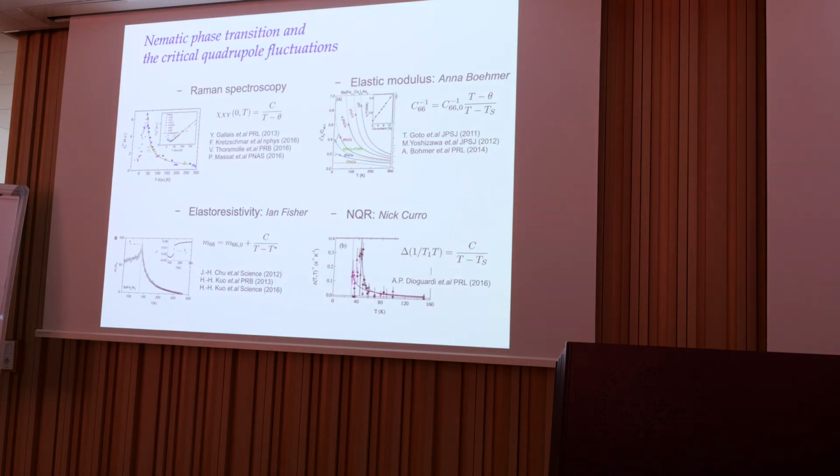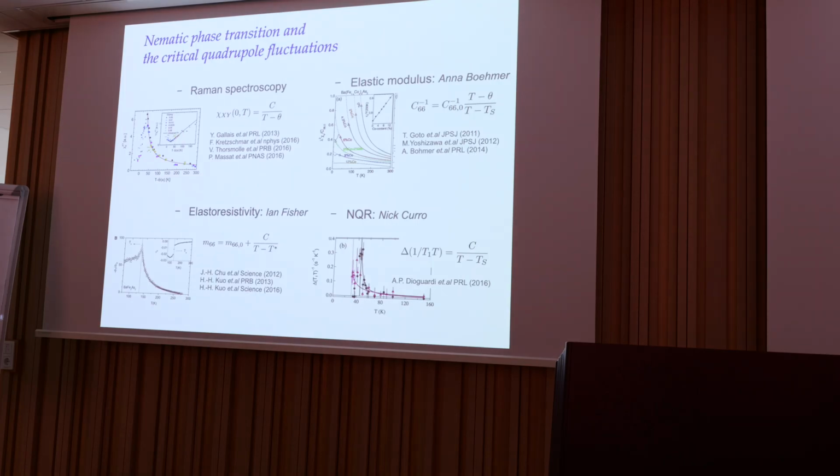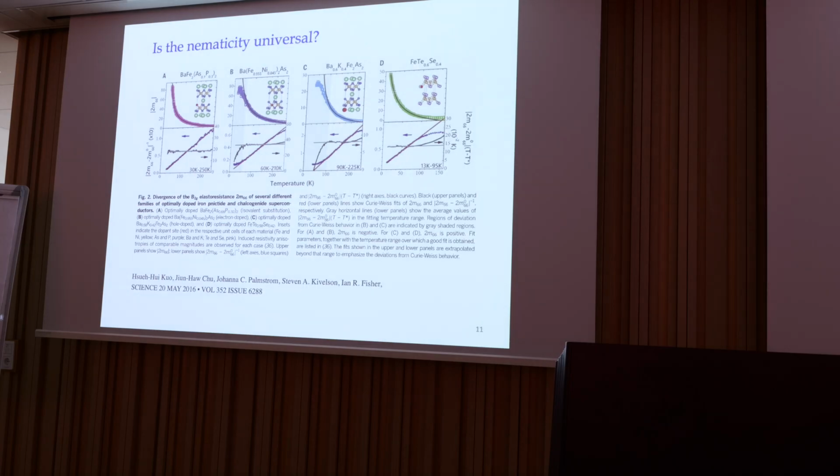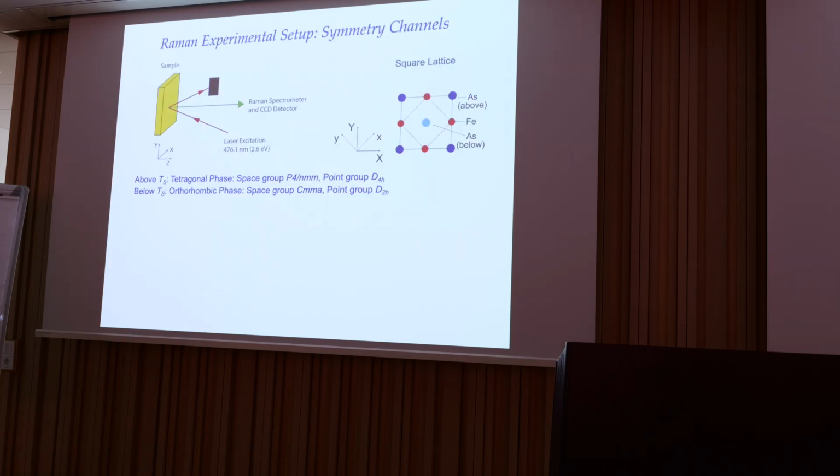So this is the limit of what can be done, and of course, almost all of these probes are Q=0 probes, so they really measure only at the gamma point, and if the instability happens at finite Q, then inelastic X-ray needs to be approached, and so on. Okay, so it's a universal phenomenon, present across all the compounds that I showed in Taka's phase diagram. There is no exclusion, or almost none.